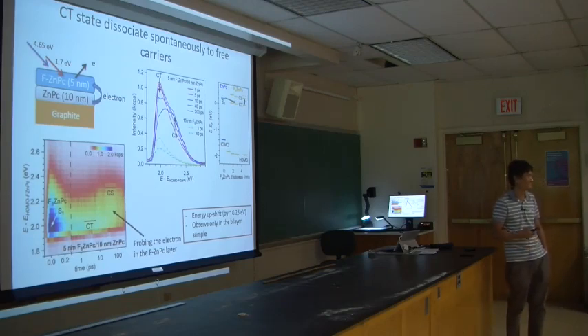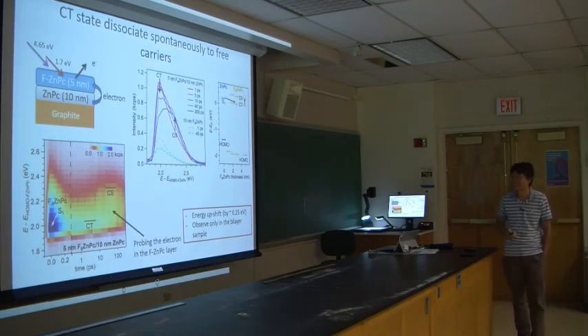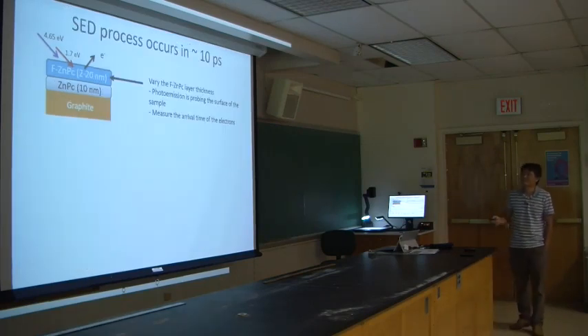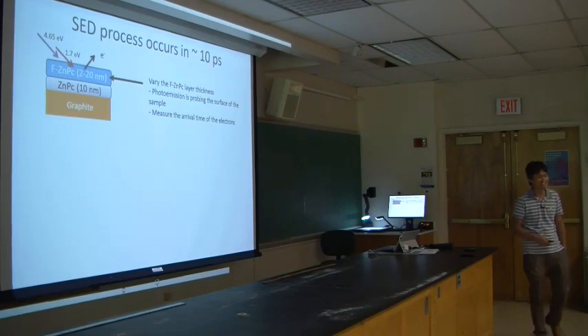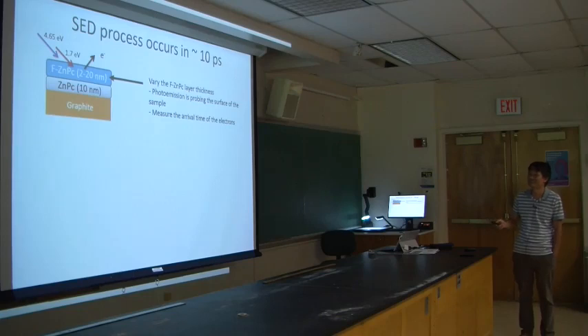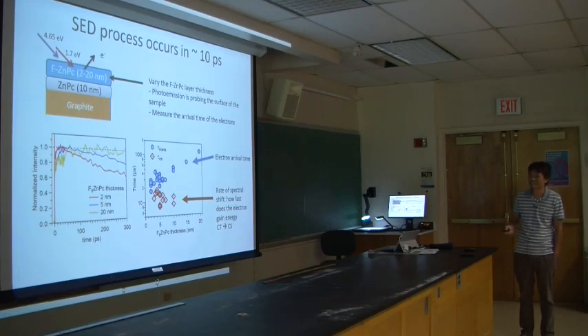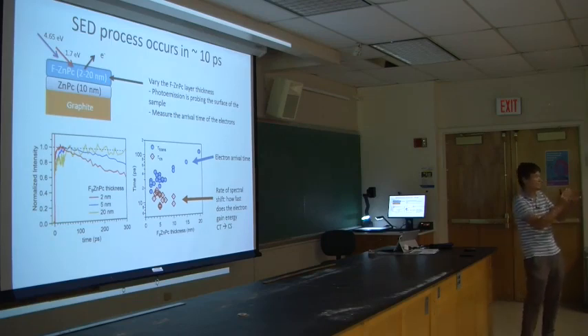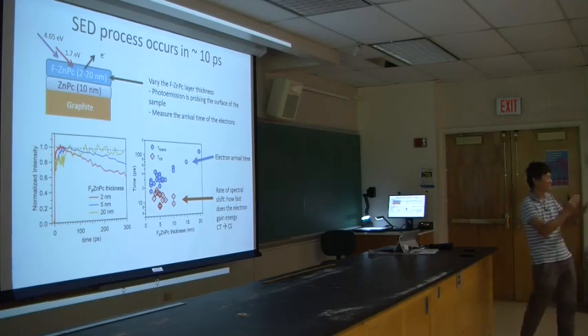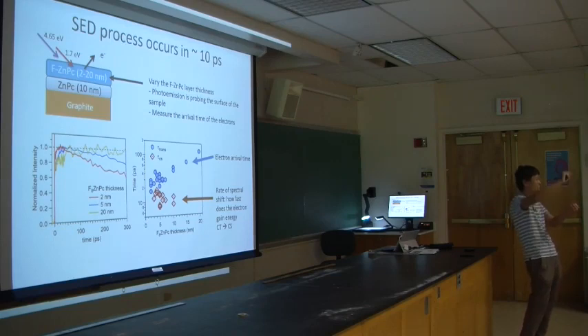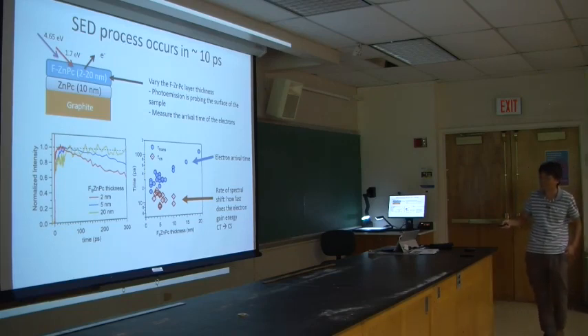So we are driving somehow these energy uphill reactions, right? So what's happening, and it occurs really fast, right? If it were slow enough, okay, it could be some kind of thermally activated behavior, but it actually occurs at a really fast rate. So what's happening? Of course, to measure that rate, we can again vary the thickness of this layer, and then we probe the electron at the surface. We can see how fast the electron comes up to the surface, which is the transport time here. We can also see how fast the spectrum shifts in energy, right? That shift in energy is actually the energy uphill process, right? So we can measure that as a function of thickness too.